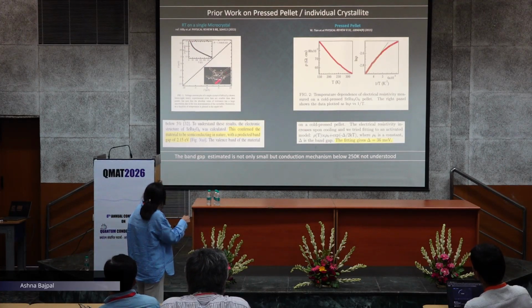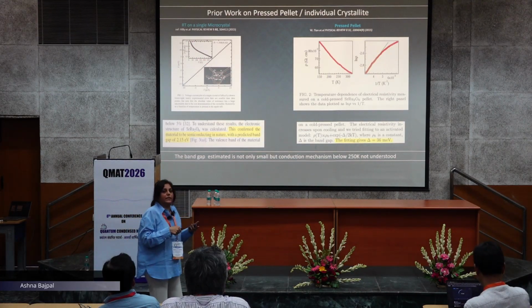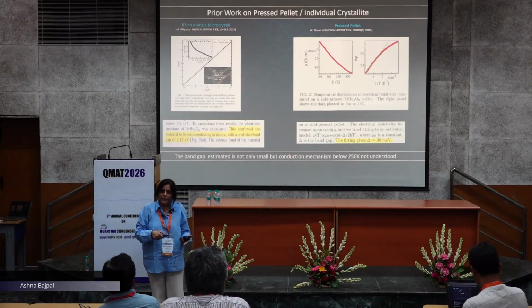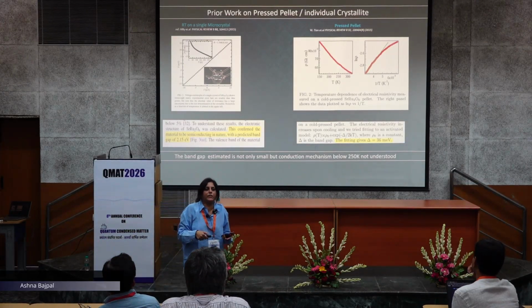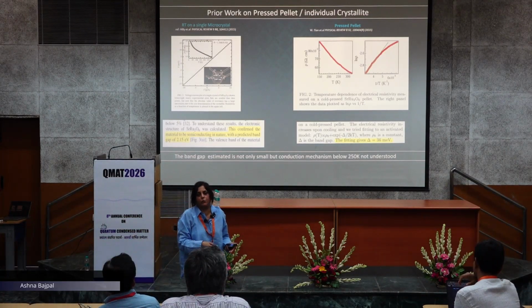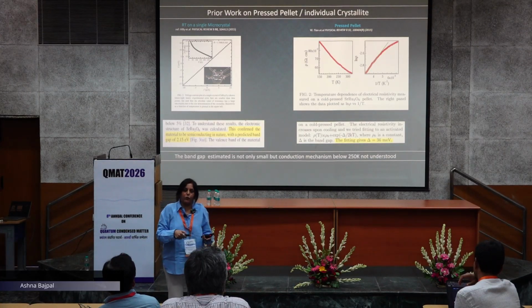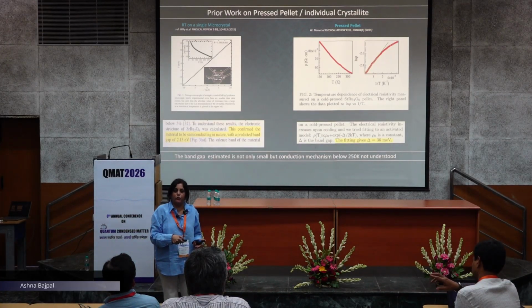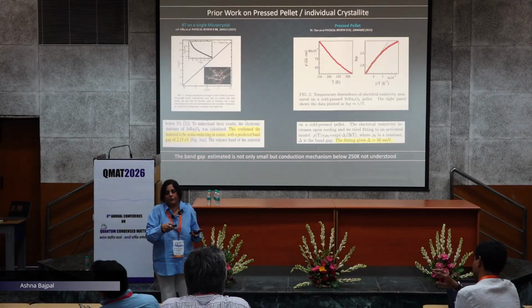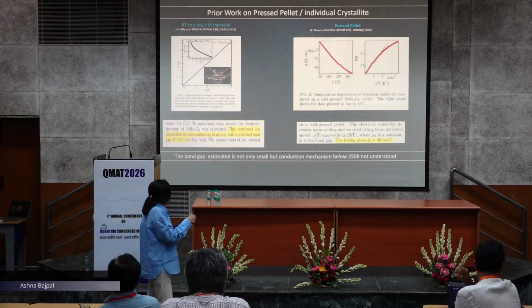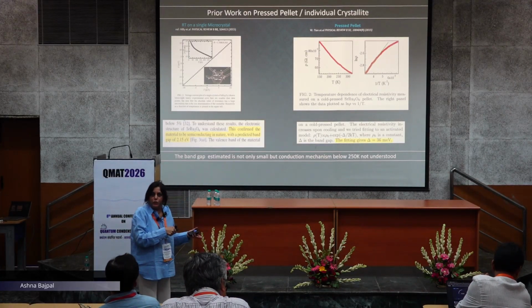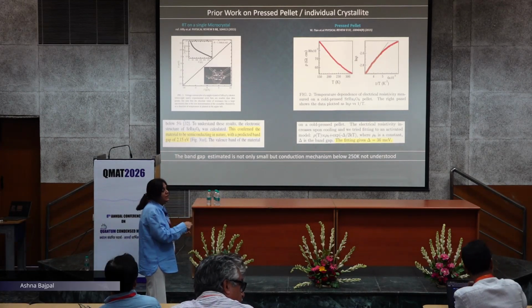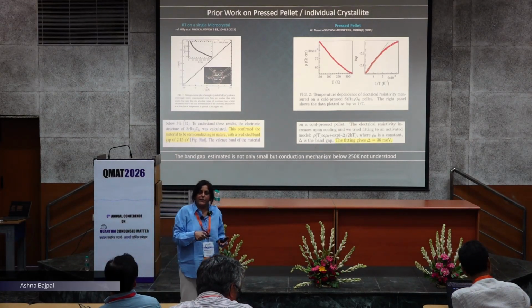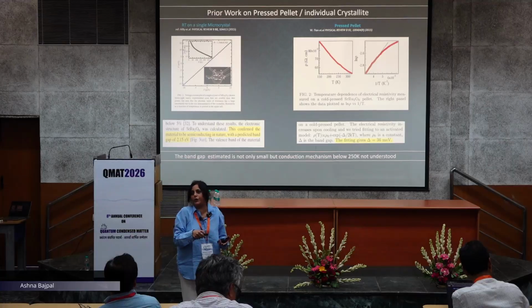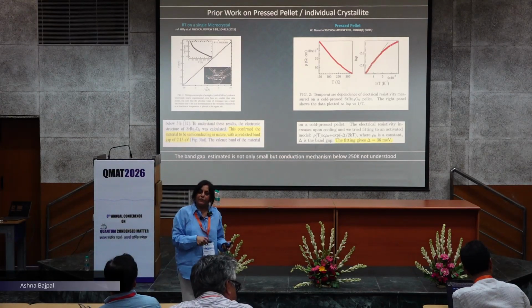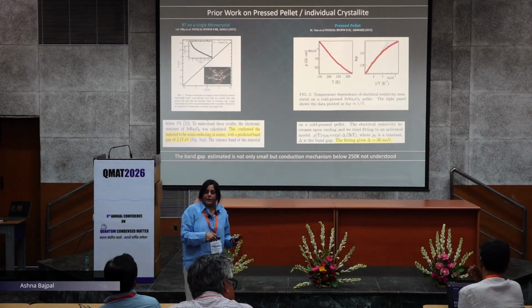with a very interesting thing, that DFT says it is a p-type semiconductor, in which depending on whether you include SOC or not, or include magnetism or not, the band gap varies from 400 to 500 milli-electron volts to 2 electron volts, as in different papers. But all experimentalists, though there are very few reports, find the band gap from the Arrhenius fitting to be of the order of 30 to 40 milli-electron volts, which is significantly lower than the theoretically predicted value.